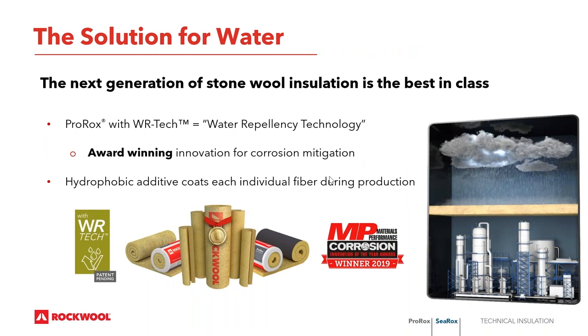So what is Rockwool's response to this challenging topic of corrosion under insulation and the need for water repellency in insulation? Well, we developed the next generation of stone wool insulation. This innovation is referred to as ProRox with WR Tech, which stands for Water Repellency Technology. WR Tech is an advanced technology based on a unique binder that repels water. It is a hydrophobic additive that coats, as I mentioned, each individual fiber of the stone wool insulation, and that's done during the production process.